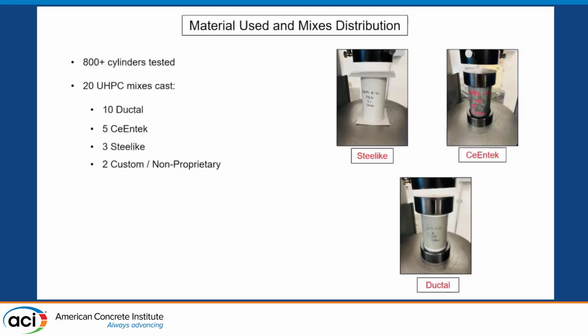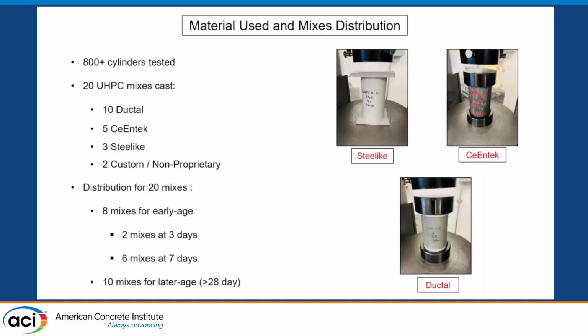And so the materials which we used were proprietary mixes from UHPC manufacturers: Ductal, CeEntek, and Steelike. Our mix distribution comprised 8 early age mixes with 2 super early age, and then 10 later age mixes, which is 28 day or greater. In total, we cast and tested over 800 cylinders.